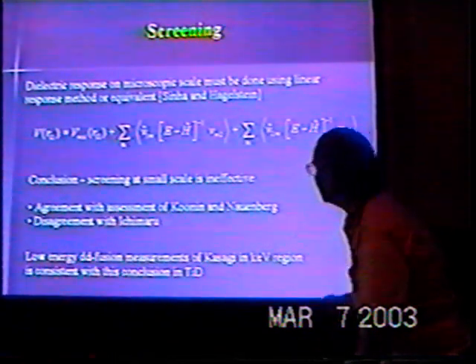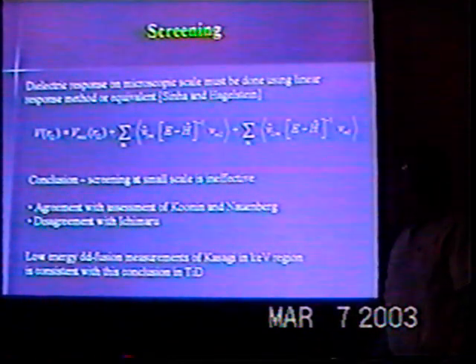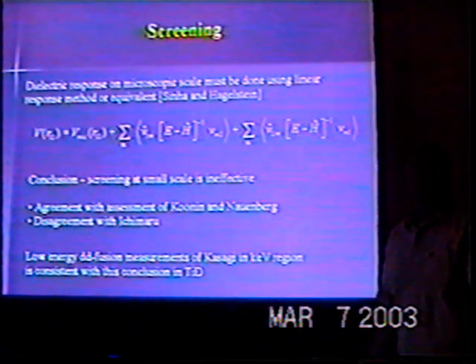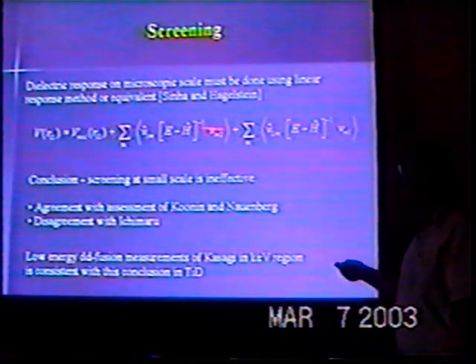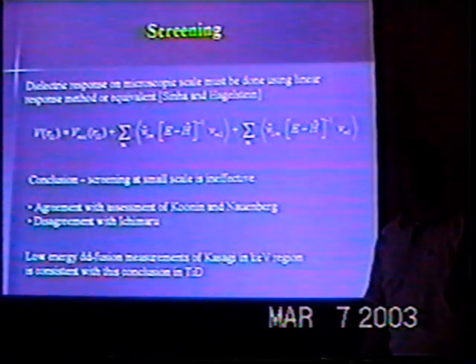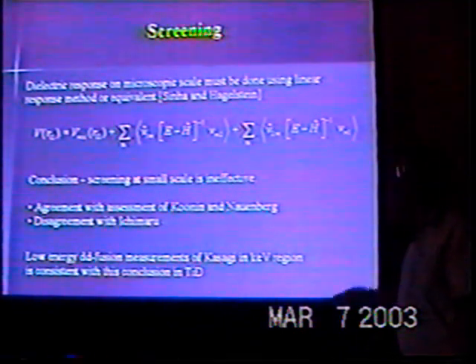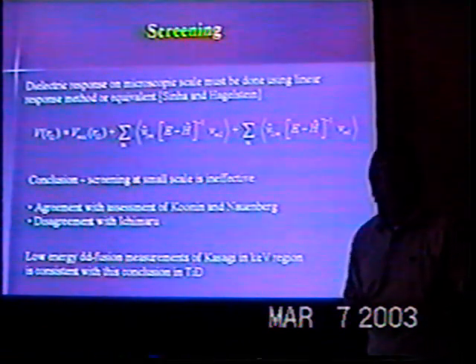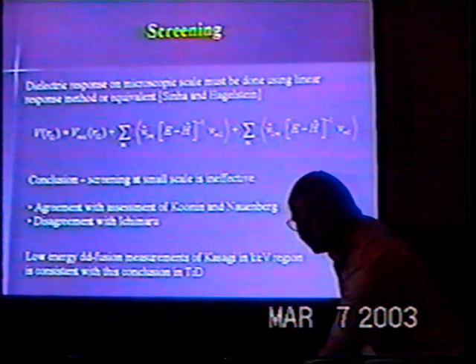Basic idea is that the molecular result is what I would expect in a metal deuteride. Ichimaru has proposed that you can have screening in the metal deuteride, which gives you much larger tunneling rate. KP Sinha and I cooked up a linear response model for the dielectric response between 2 deuterides in a metal deuteride. And the conclusion is that the screening at 100 Fermi distances, very small distances, is no different than from the molecular case.